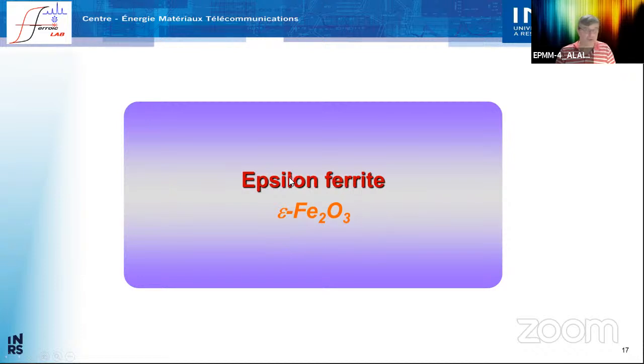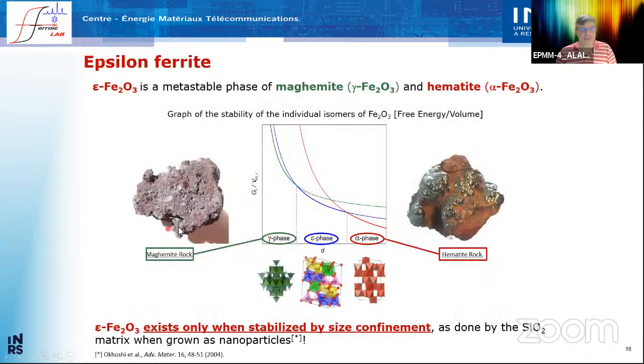material, which will be, of course, very, very interesting because it's only iron and oxygen, non-toxic, abundant, and very well known, but it's the metastable epsilon phase. This material is actually an intermediate between the alpha phase, which is the hematite, and the maghemite, which is the gamma phase. And it's stable only in a very, very small region. And that's why we have, up to very recently, only nanoparticles of the epsilon ferrite, the epsilon phase of Fe2O3.